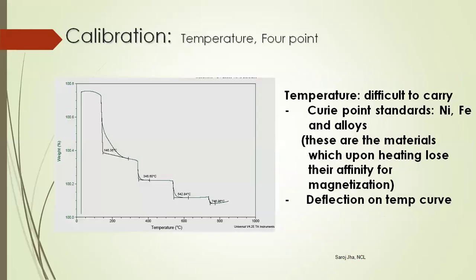So there are two types of calibration. Of course, temperature calibration. For the temperature calibration, your manufacturer has given, along with the instrument, Curie point standards. What are Curie point standards? These are metal alloys which lose their magnetization upon heating. So there is a sharp weight loss at a particular temperature, and this is a point to see whether your machine is calibrated for the temperature.